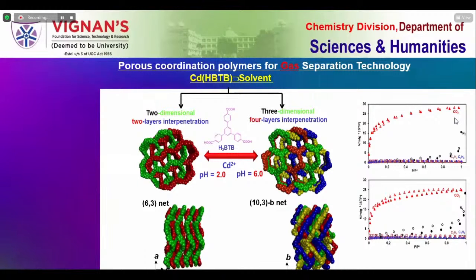Okay, so with the same BTB ligand, we then tried to react with other metal salts like lanthanides or actinides, the f-block transition elements. Then we got very big porosity in this case compared to the previous case. You can see very big, robust porosity, and moreover this can absorb a variety of gases. Based on the properties of the porosity, we can separate methane very beautifully from carbon dioxide, and methane from ethane. In fact, separation of methane from ethane is very difficult, because they are very close in size, and their physical properties are also very close, because both of them are hydrocarbons. But you are able to separate them 100%.